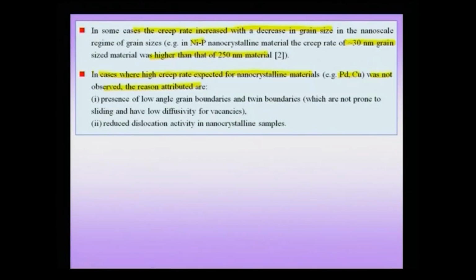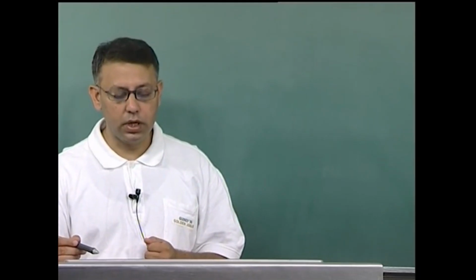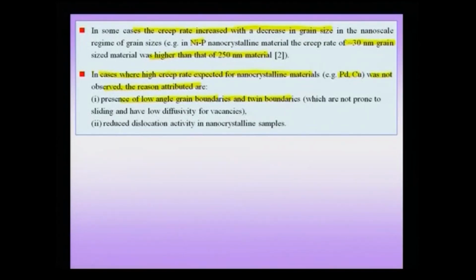The reasons are typically attributed to the presence of low angle grain boundaries and twin boundaries. And these low angle grain boundaries are, as you know, low energy configurations, and typically low angle grain boundaries by the Read-Shockley model are decorated by structural dislocations, which actually accommodate the misorientation. These are not prone to sliding and have a low diffusivity for vacancies. Therefore, because there is a predominance of these low angle grain boundaries, there is a theoretical basis for understanding why such a material, in spite of being in the nanoscale, does not show high creep rate. And additionally, low dislocation activity is also being attributed to this low creep rate.